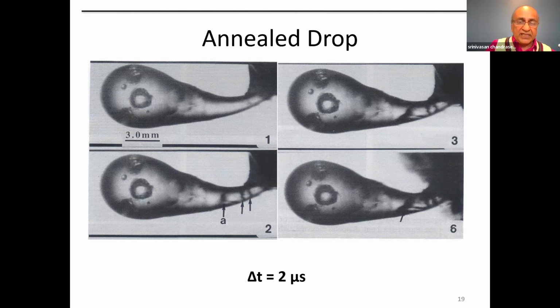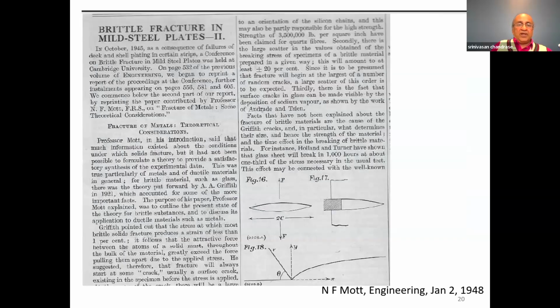So where you see the letter A and then a couple of arrows, little fractures develop, and then the head of the drop just flies off, and the right-hand side, the tail, stays intact, and we could actually recover the head intact without any disintegration. So annealed drops don't disintegrate like non-annealed drops. So that again shows that stresses are the reason. And so this is to rule out that the explosion is also the cause of any hanky-panky here.